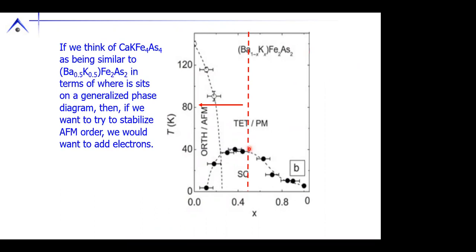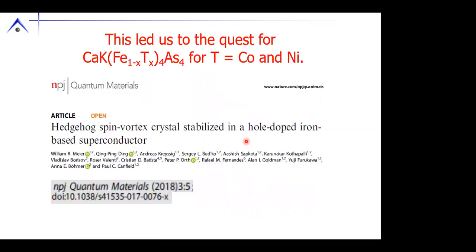If we have 50% potassium substitution, that puts us at this part of the phase diagram. Well, 50-50 barium potassium is the same electron count as 50-50 calcium potassium in this true quaternary material. If we take that as our inspiration, it says if we're able to add electrons, we're able to then move backwards, and we might be able to discover the magnetism or the structural phase transition or the whatever that this superconductivity is coming from.